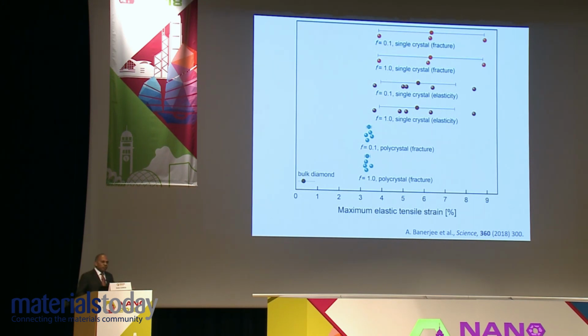Of course, when we create diamond needles by etching like this, there is a variation in geometry, a variation in friction, a variation in height, etc. So it's not surprising that you get quite a bit of variability in experimental data. What you find is that the maximum elastic strain in the single crystal case is between 4 and up to 9%. We also did experiments in polycrystalline diamond, where the scatter is much smaller, and you can see the data for elasticity and in the case of fracture. We did two friction coefficients, 0.1 and 1.0, and in both cases, in polycrystalline diamond, you get a maximum elastic tensile strain of about 3% or so. For comparison, bulk diamond has a much, much lower tensile strain as expected.